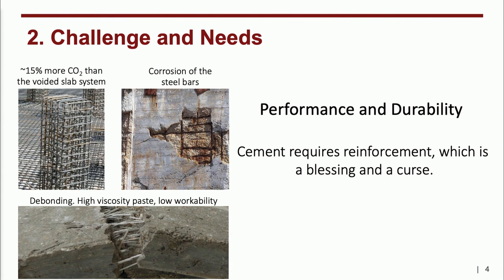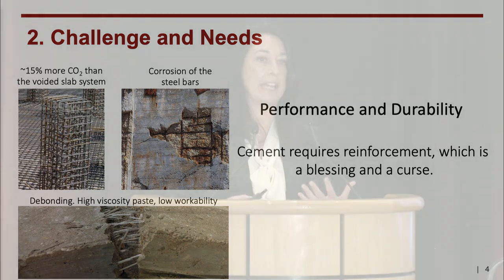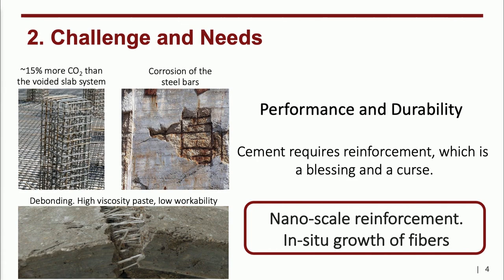And then there is another problem. The more fibers we have, the better, because the strength and the ductility of the material increase, but then the greater is the viscosity of the paste, which brings lower workability of the slurry. So what if we decide to reinforce the cement at the nanoscale by growing fibers in situ?